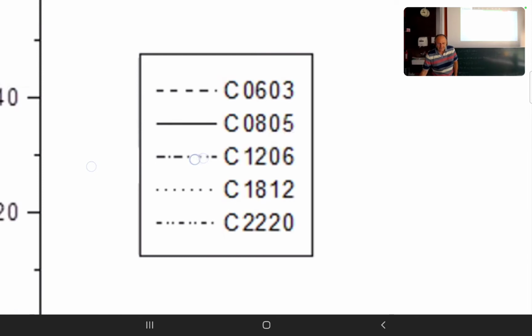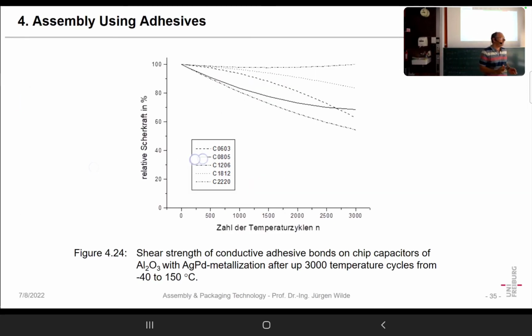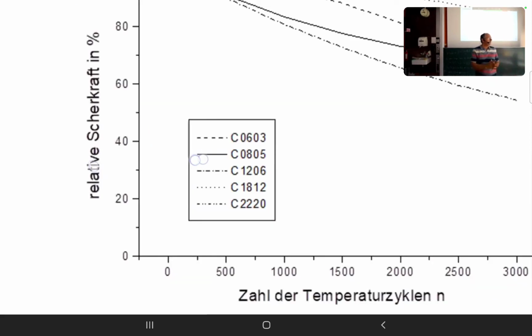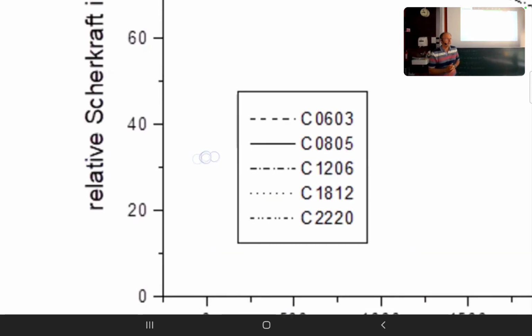And what we did is these devices were just sheared off. We have also at the intake a shear tester. The devices are sheared, and the shear force is recorded. And then, of course, it must be on a statistical basis. For instance, we have 10 or 20 specimens which are the same. And then we take the mean value, and then we can record the shear strength as a function of cycles.